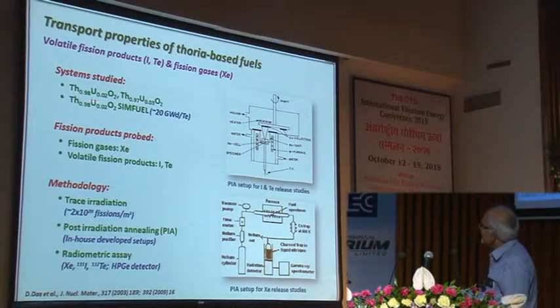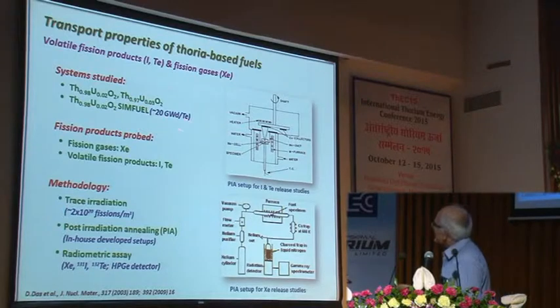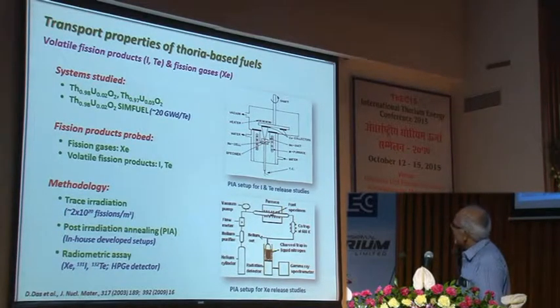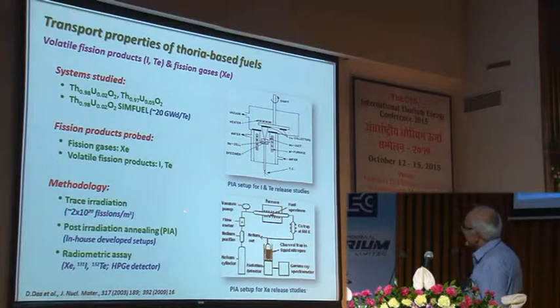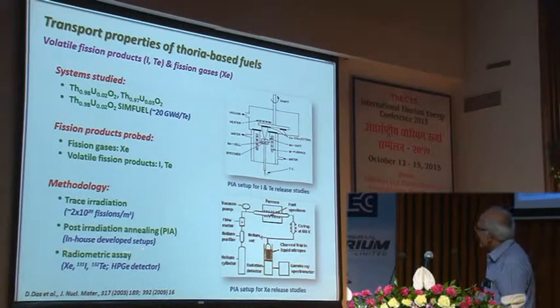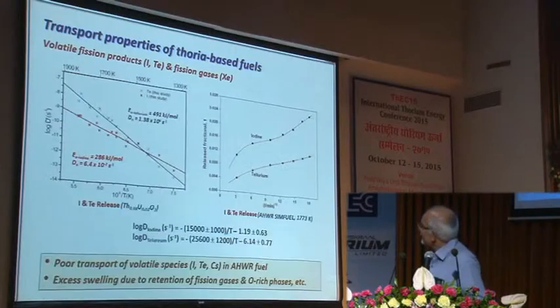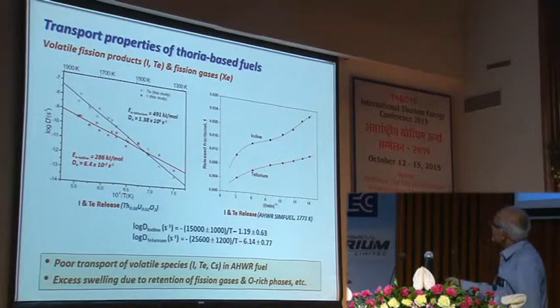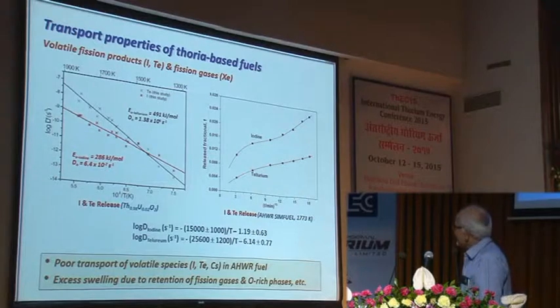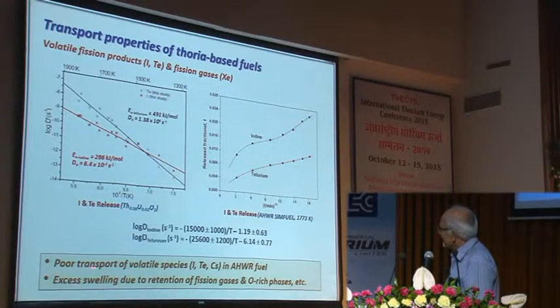This is the virgin fuel, and these are sim fuels corresponding to 20 gigawatt day per ton burnup. The fission products probed are xenon, iodine, and tellurium, and the methodology followed here is trace irradiation, about 2 into 10 to the power 20 fissions per meter cube, then post-irradiation annealing and radiometric assay. These are two setups here. This one is for iodine and tellurium release studies, which are collected on copper collectors, whereas for xenon it is charcoal trapped in liquid nitrogen. And these are the diffusion coefficients, the transport properties we evaluated. We identified poor transport of volatile species, that is iodine, tellurium, and cesium, in AHWR fuels, and there is excessive swelling due to retention of fission gases and oxygen-rich phases.